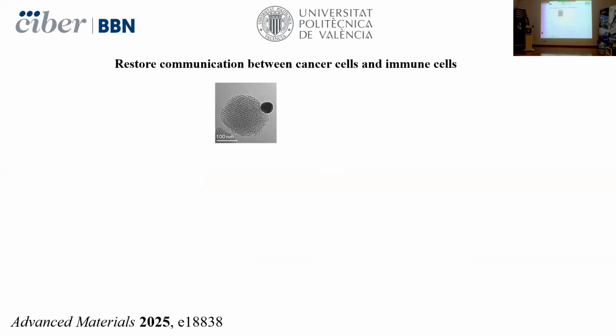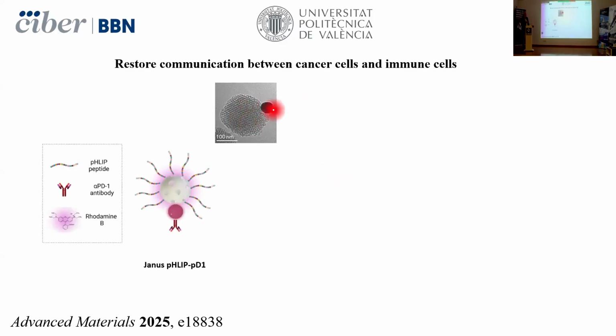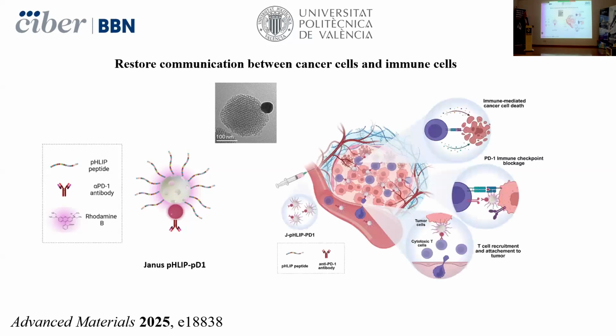That was the idea. We designed a quite simple nanoparticle, again a mesoporous silica nanoparticle attached to a gold nanoparticle. This is a Janus nanoparticle. Then we anchor a PD-1 antibody on the gold face, to target T cells, and we put here just a peptide. This is the pH low insertion peptide, which is very well known because it intercalates in the membrane of cancer cells. So the idea was quite simple: to see if those nanoparticles could bring together tumor cells and T cells, so that T cells attack the cancer cells again.